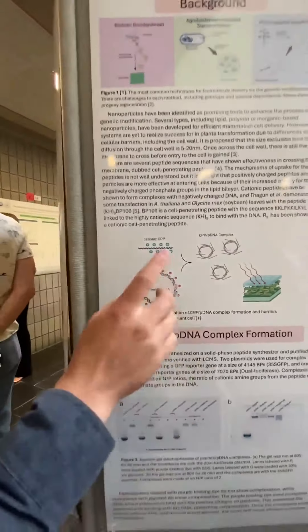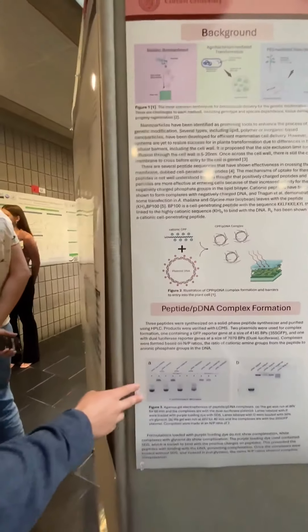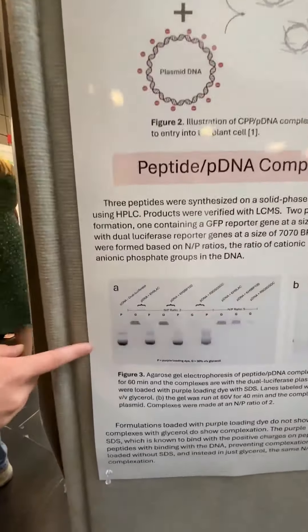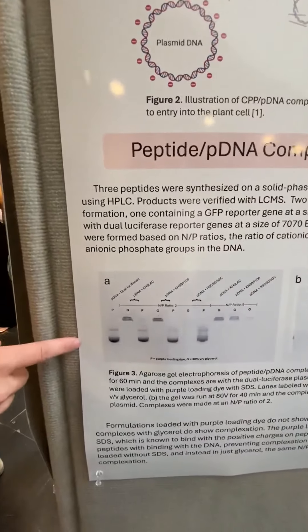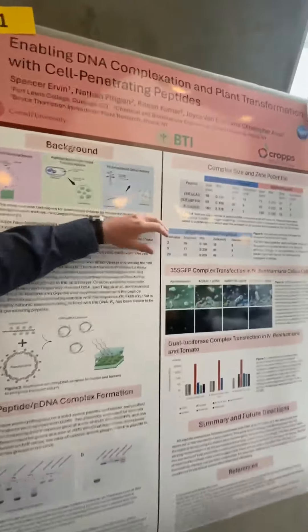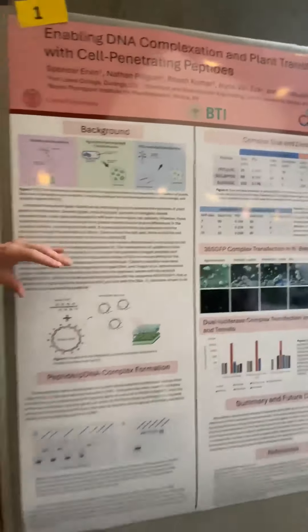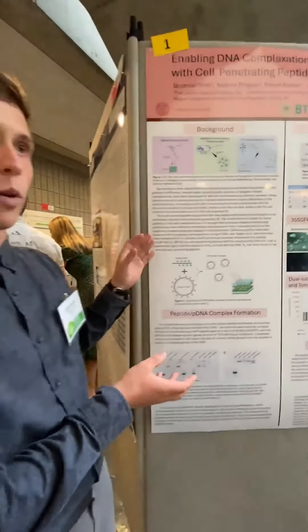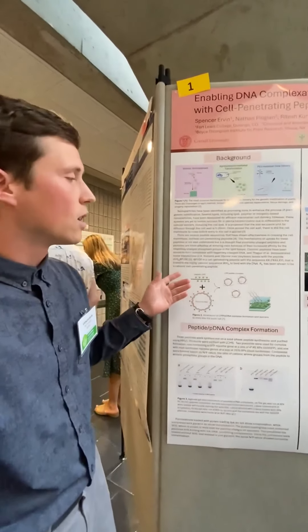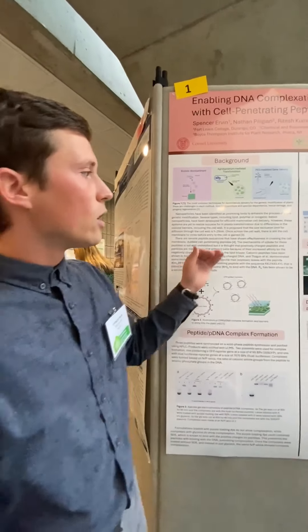We characterized those nanoparticle formulations with agarose gel electrophoresis and dynamic light scattering, which gave us an idea about their size and to make sure we were forming the complex the way we'd expect.